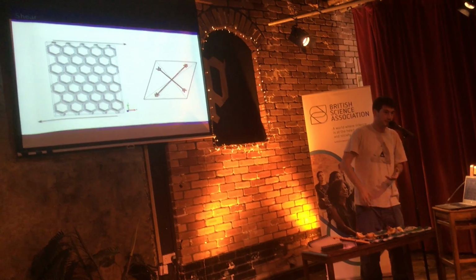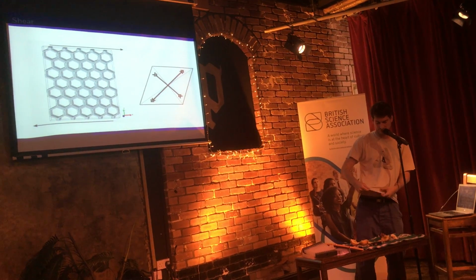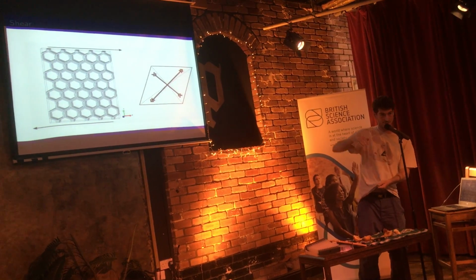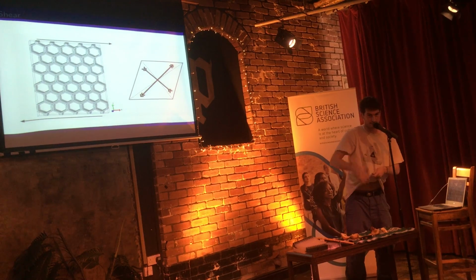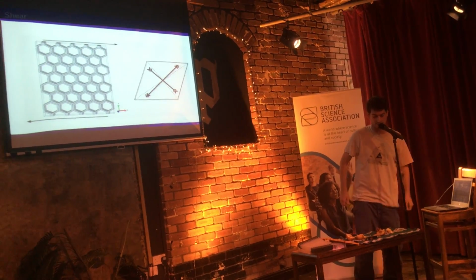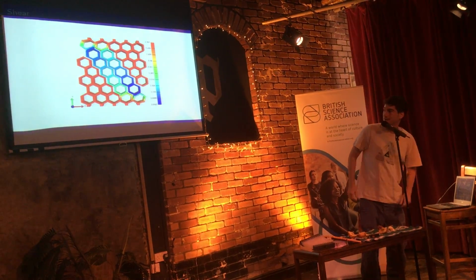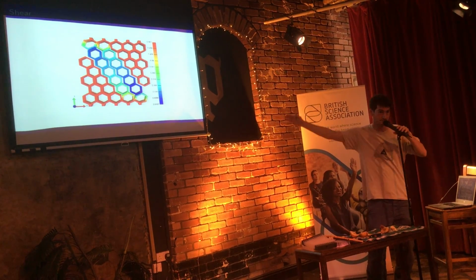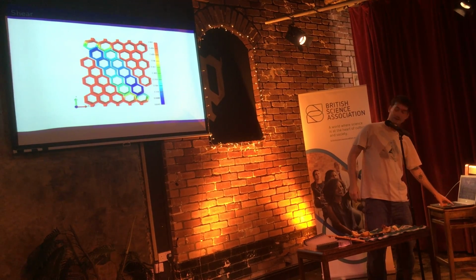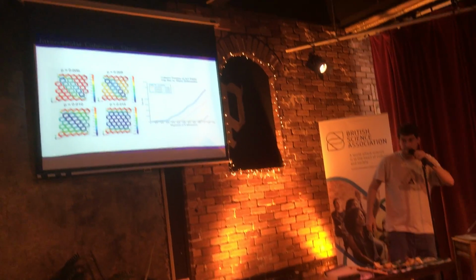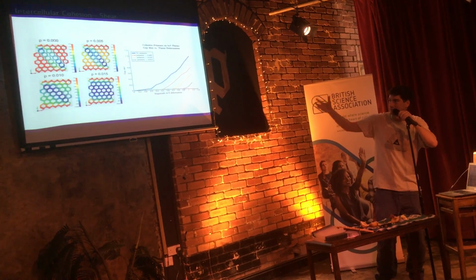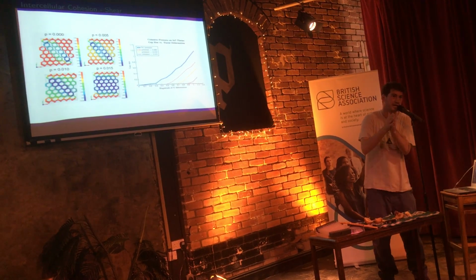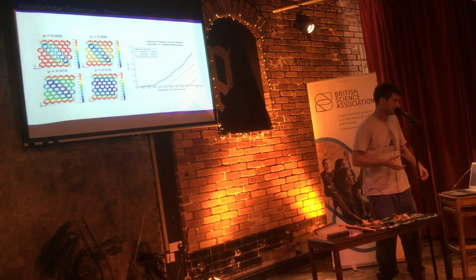One good way of doing a little test for yourself is if you grab your shirt and you pull it one way and push it the other way. You notice there's some rolls that occur, and then it's also being pulled in the other direction. And that's kind of what happens in this material. We have these diagonal cracks that open. And as we vary the cohesion, as you'd expect, the stronger the cohesion, the smaller the gap, and the more it kind of sticks together.